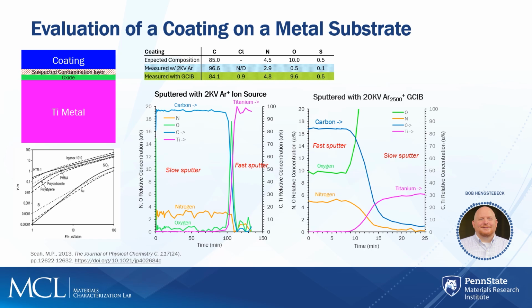And so had we tried to sputter this with the initial 2 kV source, a couple of things would have happened. One, the sputtering was very, very slow, and so it took a long time to get through to the interface. But also, that material, just like the polystyrene, formed an amorphous carbon, and we actually lose some of the information that was in the coating. We'll talk about what that looks like in a moment. But essentially, we lost that information. And then when we finally did hit the interface, we got through the interface so fast that we couldn't actually see what was going on.